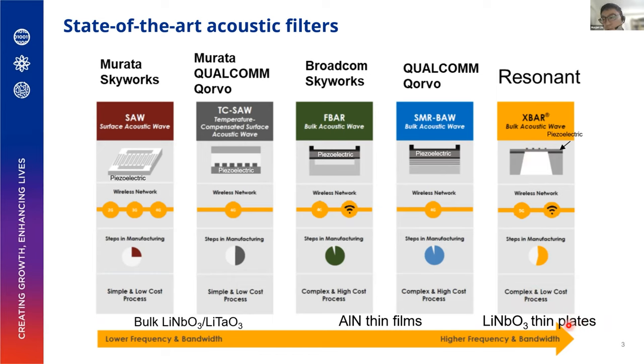So these are not thin films, because this is actually using some kind of technology called smart cut to transfer a very thin layer of lithium niobate from the single crystals. And then you put it on silicon oxide, silicon wafers. So this also has a cavity on the backside. So this device actually can have a much higher operation frequency and much wider bandwidth. So this is a new architecture. I believe it has not been mass produced yet. So these two are actually what we use in a lot of high-end mobile communication products.